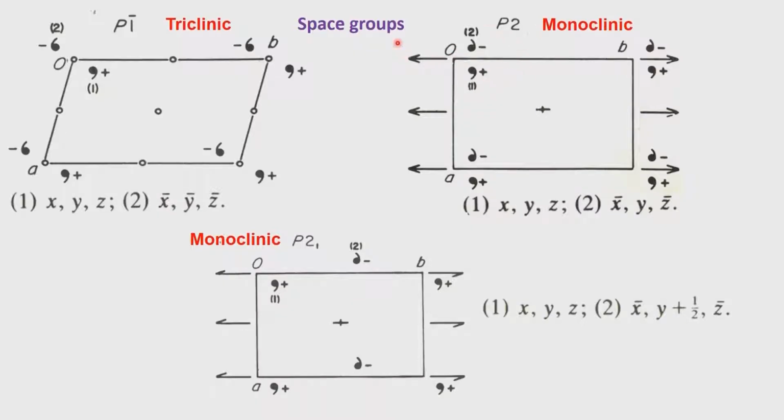What is shown generally in all projection diagrams, including the International Tables for Crystallography, unless otherwise specified, is that the projection is down x is A and down y is B, and C is coming either perpendicular or going inside the board in a perpendicular direction. In the case of a monoclinic system, it is not necessary that it should come in a perpendicular direction.